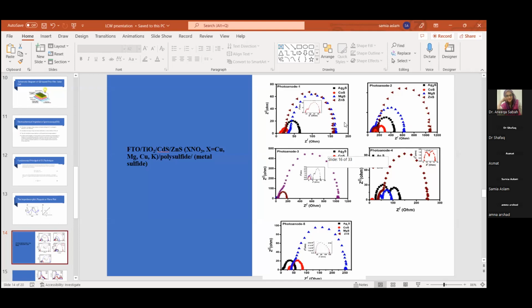So electrolyte will definitely gain electrons from the collector side, which is the counter electrode. So it means that we might divide it into two interfaces where we can see that the bigger circle or the low frequency region represents the counter electrode electrolyte interface, and the high frequency region represents the electrolyte and the photoanode interface. So in this way, we can understand the mobility of various charges inside. And as you can see, since this is an impedance plot and its x-axis represents the real part of the resistance, the width or diameter of this circle represents the resistance being offered to the charge flow in that particular region.